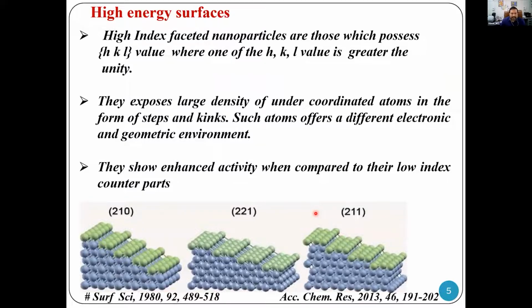You can also have high energy surfaces, which have high index, possessing hkl values higher than 1, and then they expose a large density of undercoordinated atoms in the form of steps and kinks, which I mentioned in the previous slide. Such atoms present on the surface can have a different electronic and geometric environment, which provides a different kind of activation barrier for molecules with which they interact. And because of the presence of these defective surfaces, they can show enhanced catalytic activity compared to their low index counterparts. So this has been the motivation behind starting this work when I joined NCL.